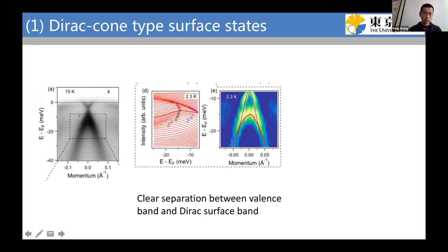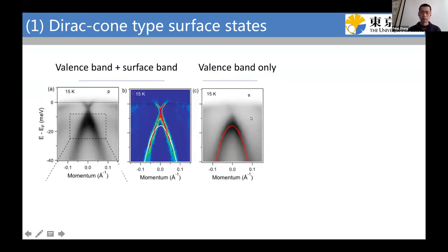If we take a closer look at this small region from this raw EDC data, we see that there are two peaks. The lower peak is the parabolic band, and the upper one is the lower Dirac cone. We can also use curvature or second derivative to increase the contrast. Then the data is more clear. The parabolic valence band, dxz valence band, and the lower Dirac cone. Also, this valence band is consistent with the valence band observed with the S-polarized light.